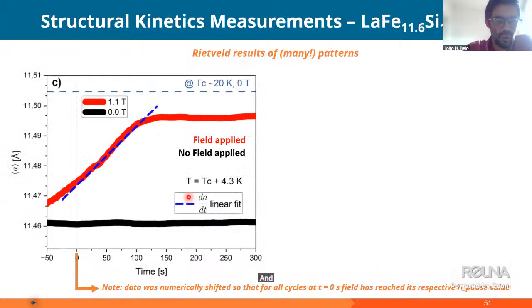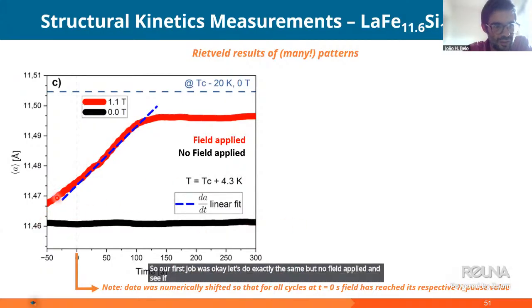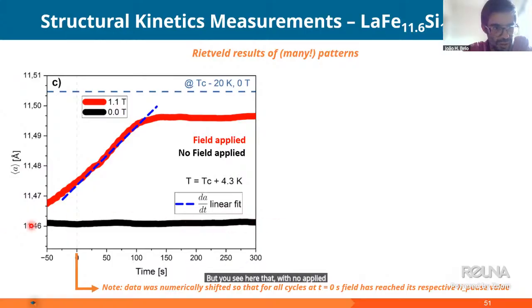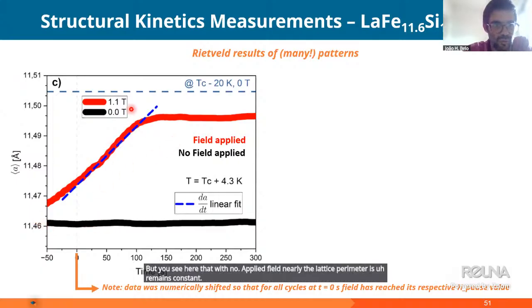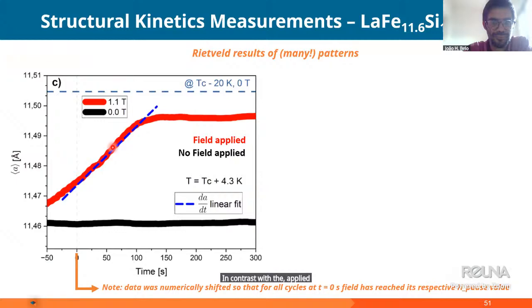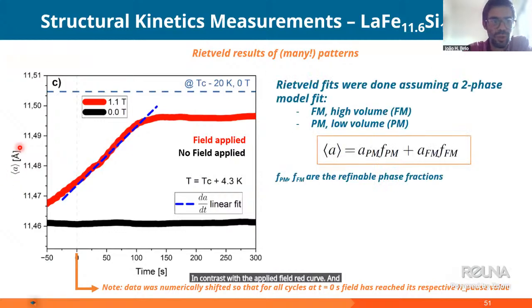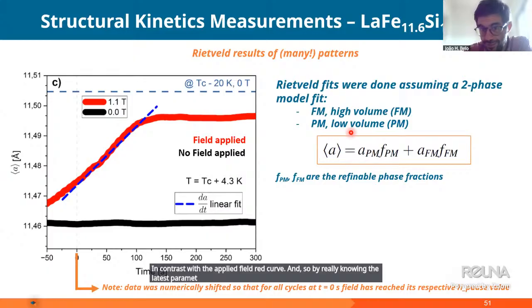And so we took this opportunity. We were very, how can I say, skeptical at the time. So our first job was, okay, let's do exactly the same, but no field applied, and see if this change in the lattice parameter is just because there are thermal fluctuations. But you see here that with no applied field, the lattice parameter remains nearly constant, in contrast with the applied field red curve.